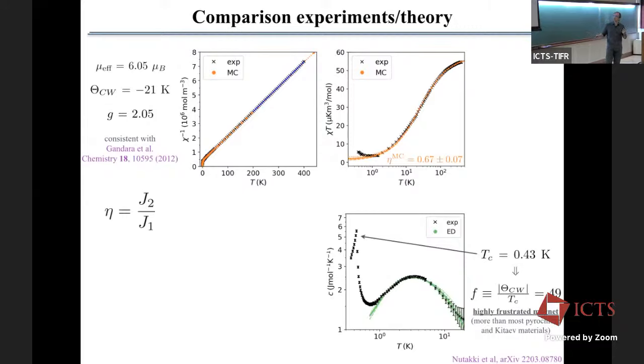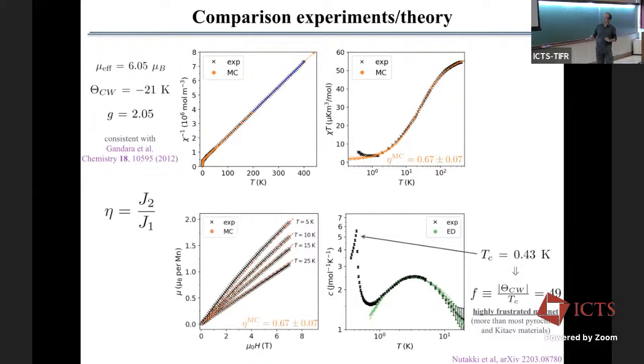When you have J1 and J2 antiferromagnet, the low temperature physics in simulations is a spin liquid. So which means that this peak here is beyond our J1, J2 model. So we have some idea about what's going on here, possibly dipolar interactions or things like this. But what I'm going to tell you about today is about a minimal J1, J2 Hamiltonian, okay? And so we have this nice fit here from 300 Kelvin down to roughly 1 Kelvin, a little bit below actually. And if you do magnetization curve, so magnetization as a function of magnetic field at different temperatures, you again have a nice fit with the same parameters from 0 to roughly 7-8 Tesla, and for different range of temperatures.